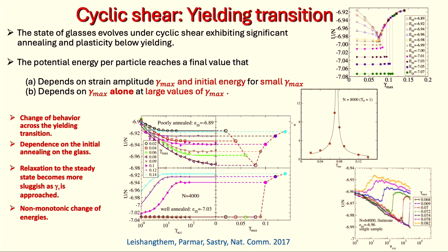Now, something that was apparent here, but I show here in a much more dramatic way, is if you look at strain amplitudes, which is my control parameter, whose values are such that eventually the system will fail, right? So all of these values for which I'm showing results here, if I look at the initial part of what happens for the initial cycles, I have behavior that's very similar to the case where I don't yield. So in other words, with initial cycles of shear, I anneal my system to lower and lower energies, and at some point suddenly I fail, okay?